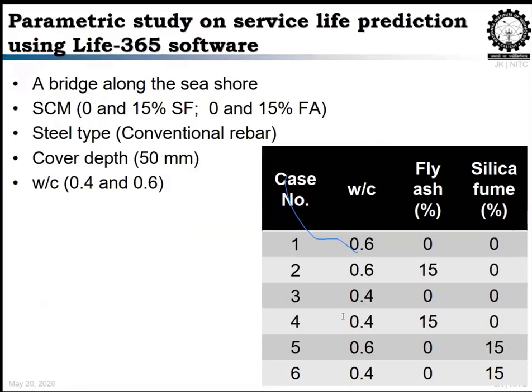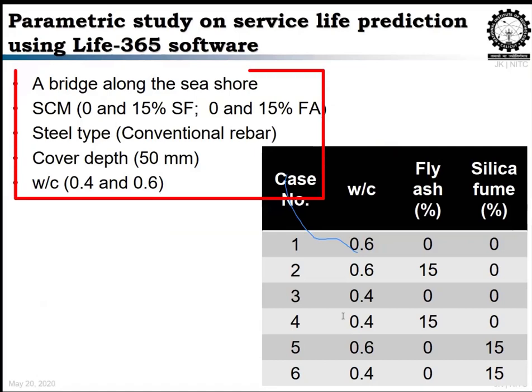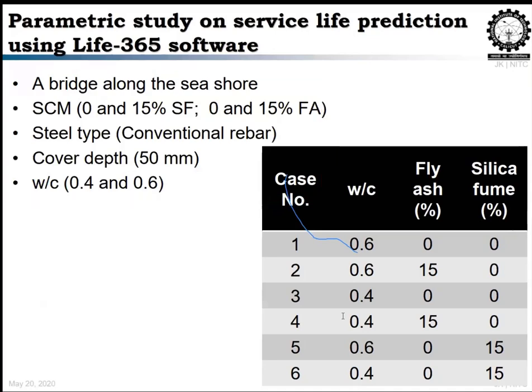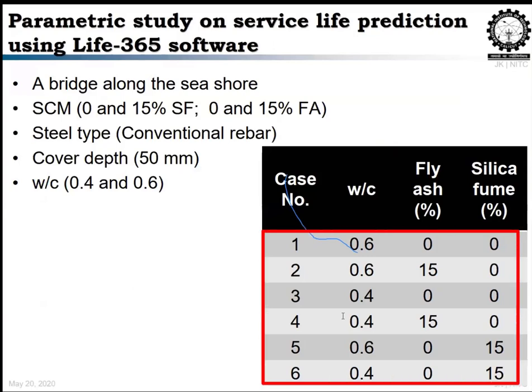So here I'll be walking through the software by taking a few cases, for example, a bridge on a seashore, which has 50 mm cover and a conventional TMT rebar, where the variability is in water cement ratio of 0.4 and 0.6. It has different secondary cementitious materials of 15% silica fume and 15% fly ash, and combinations without them. So these are the combinations. I'll do a quick walkthrough of the software.